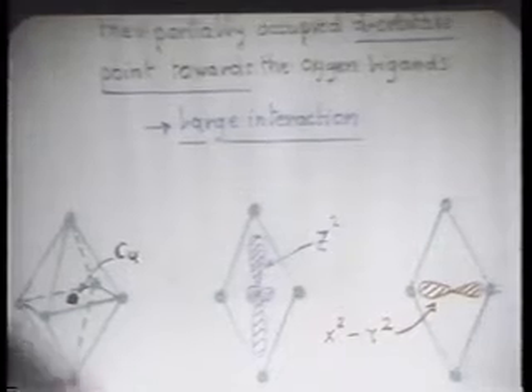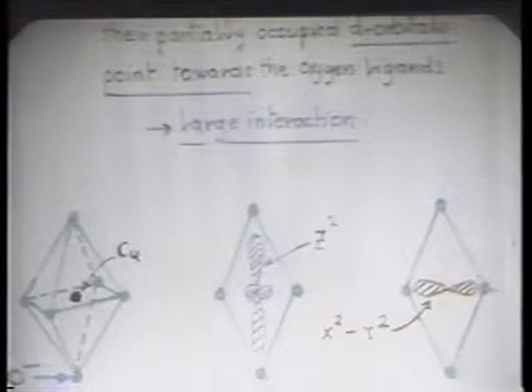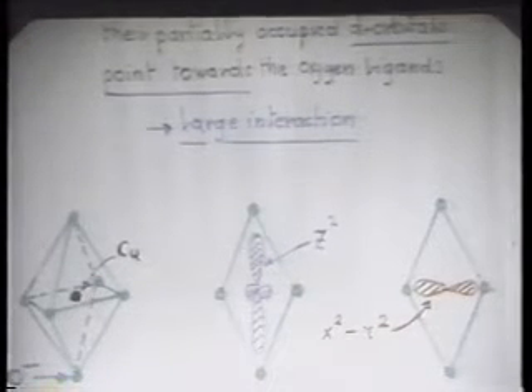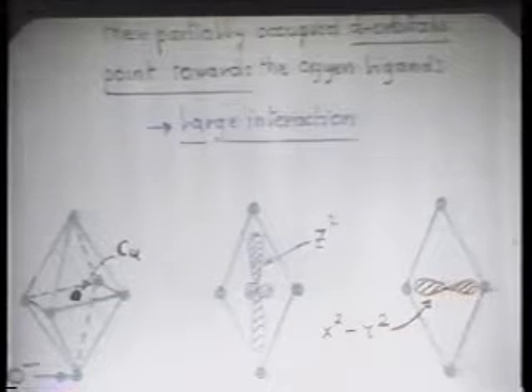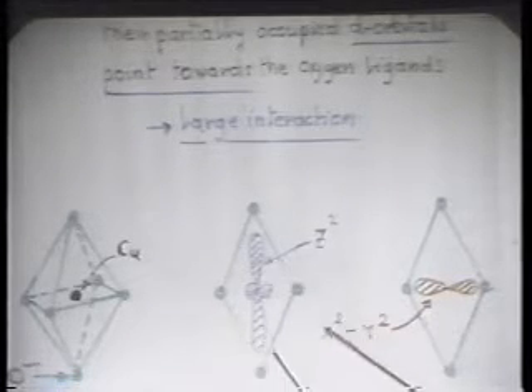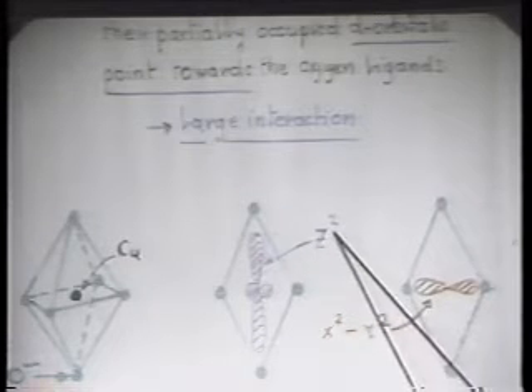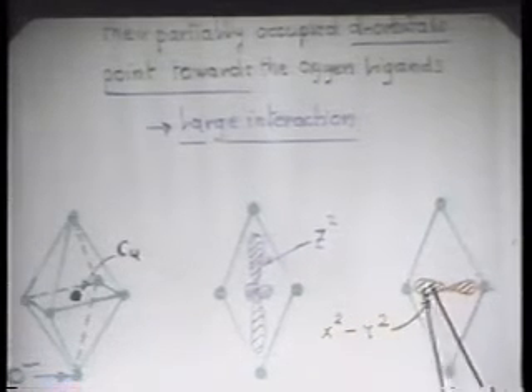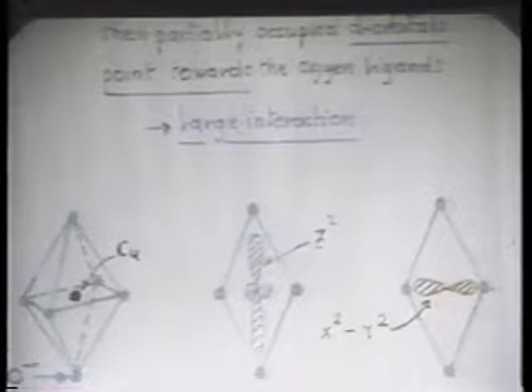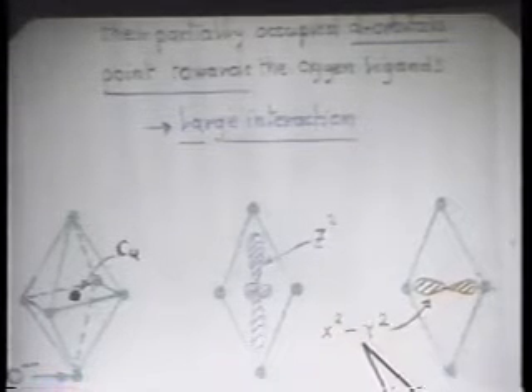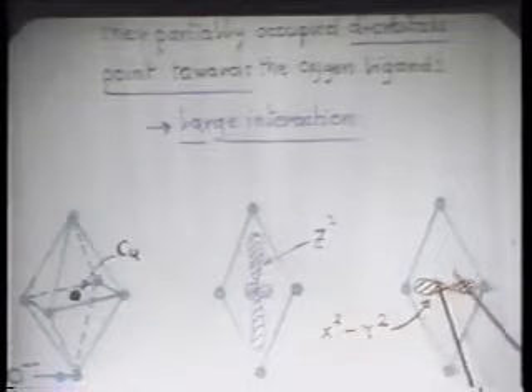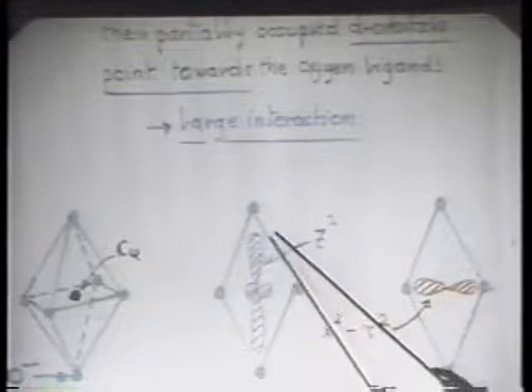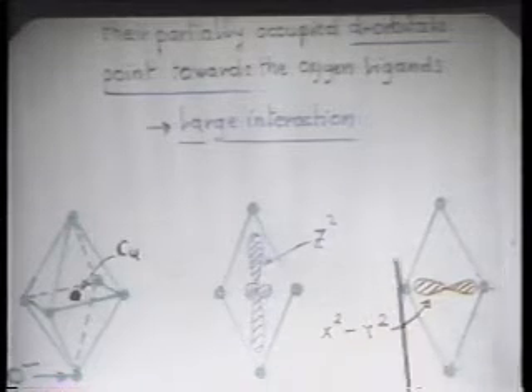You see here the octahedron and a copper inside. If you have a 3-valent copper, you have these z-squared orbital occupied and these x² minus y² orbital also occupied, and they are degenerate in energy. If you have a 2-valent copper, then the further electron goes in this orbital here, and you get an elongated octahedron. This is an expression of the Jahn-Teller effect.